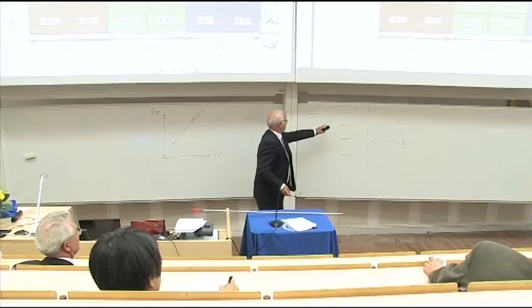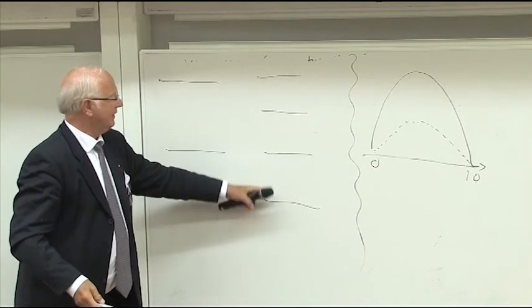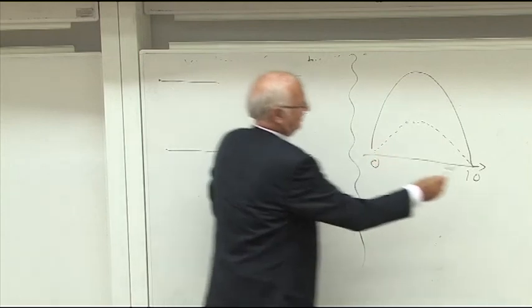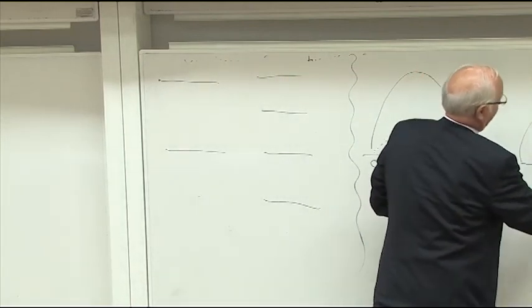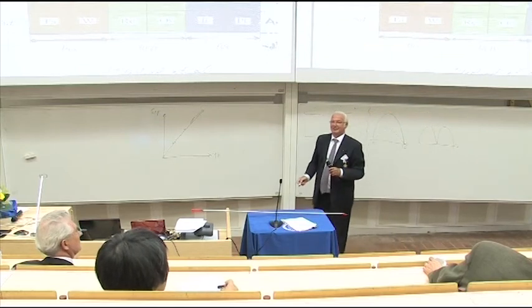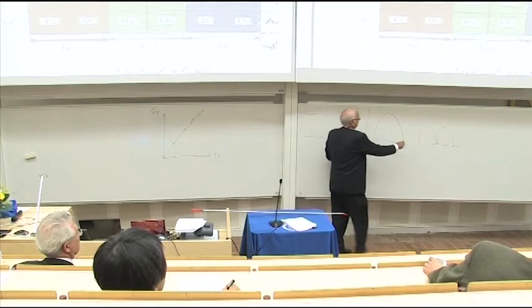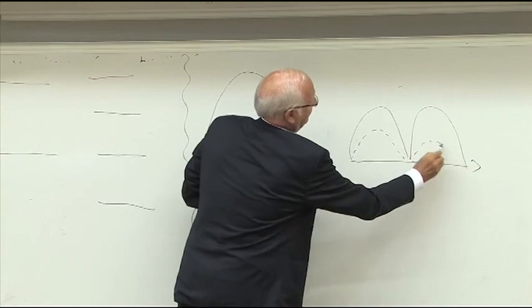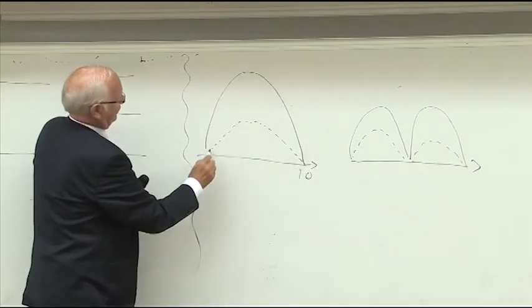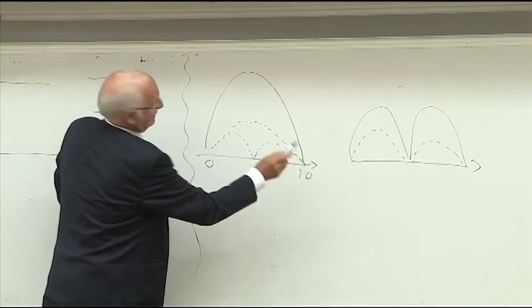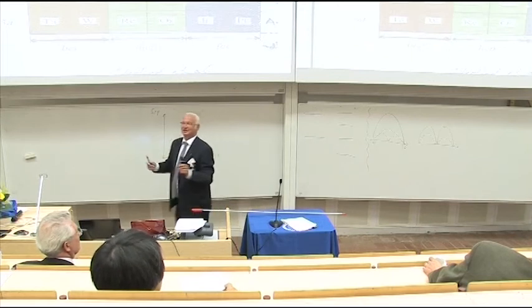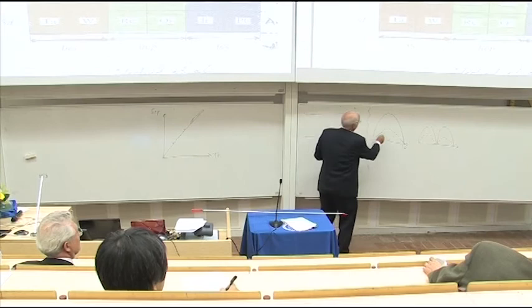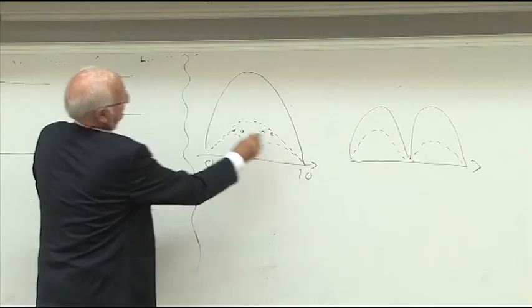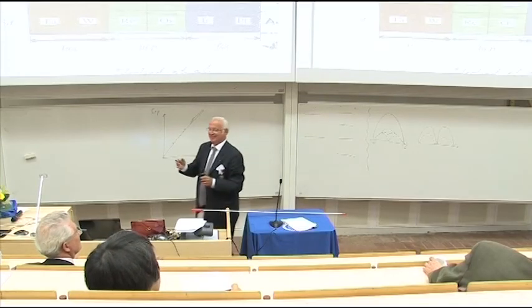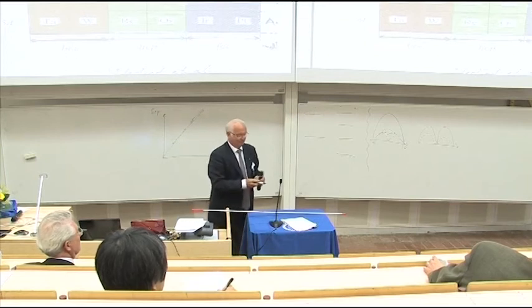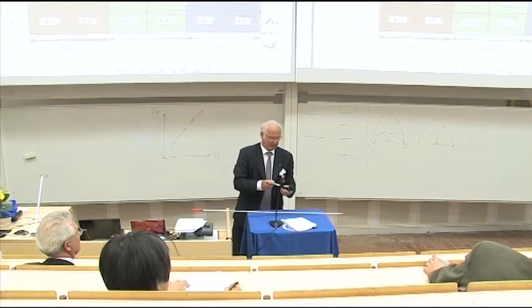Now, if we do this for this element here, when we have first fill here, then from here to there, you have one parabola for the spin down and another one for the spin up. Okay, and then of course, the surface energy will be something similar if you have saturated magnetism. So you would expect something like this. However, we know that they are not completely saturated magnets, so in reality, the values lie something like this. So it's, again, with a simple model, might be a little bit more fun to do that in order to see what the full-blown calculations are doing.